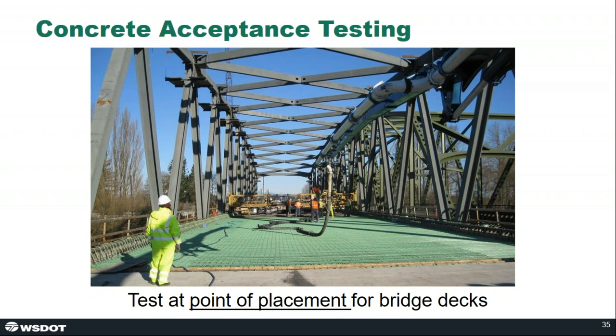And this is important. We want to be absolutely certain that the concrete going into the forms meets spec, and it's not uncommon for concrete to increase in temperature a fair amount in these pump lines and also to lose air. So the longer the pump line, the more of a challenge this becomes. It's not uncommon to see contractors hosing down the outside of their pump lines on hot days to try to limit the temperature gain that the concrete will experience.